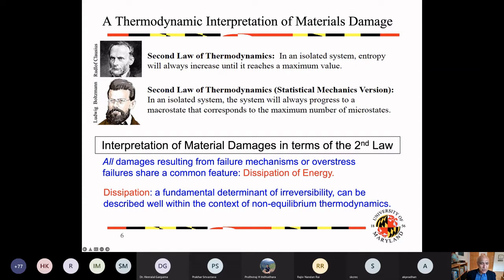So therefore, there is a very close relationship between damage and the second law of thermodynamics. And we could say that all damages occur due to some failure mechanism in materials that leads into failures, which we call in reliability, as you saw in my definition, an important time that we try to find, quantify, and predict. And that failure mechanism can be caused by environmental or operational conditions or overstresses that could lead to a failure. And all of them have one common feature, and that is dissipation of energy. They all dissipate energy. In other words, the content of energy of materials is released as the component undergoes damage.